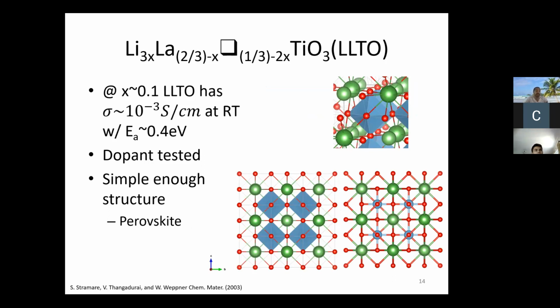One reason why we chose this one is because it has a very high ionic conductivity, which is comparable to actually the liquid electrolytes that I had mentioned that were dangerous. And so this should be like a huge hooray, like, hey, we're on the right track. One problem is that this reacts very readily with metal anodes, which these are supposed to work with. So the problem is you end up changing the conductivity of the system and make it a good electronic conductor during this situation. And so that's bad for solid electrolytes, but it's good in our case because now we have a system that we know has been proven to be tuned in terms of having higher electronic conductivity and low electronic conductivity. And the structure is simple enough in the sense that it has a perovskite structure, which is cubic, and it has an octahedral coordination for the redox site.